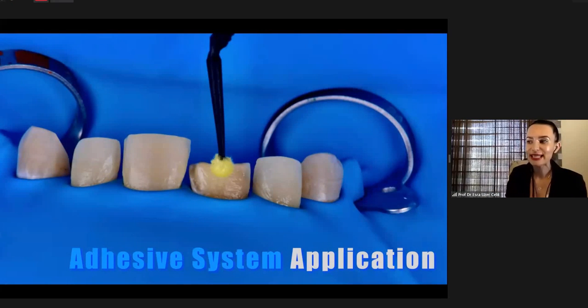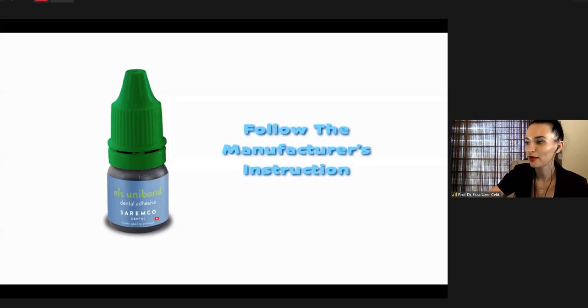And apply the adhesive system to the whole surface with a brush or an applicator. There are two differences between the applicator and the brush. The first one is you couldn't get a tactile sensation with a brush. So in posterior, I generally prefer applicators. But also applying the adhesive system into small areas, into the gaps, is easier with a brush. So I generally use a brush in the anterior region instead of applicators. Follow the manufacturer's instructions when you apply the adhesive system.